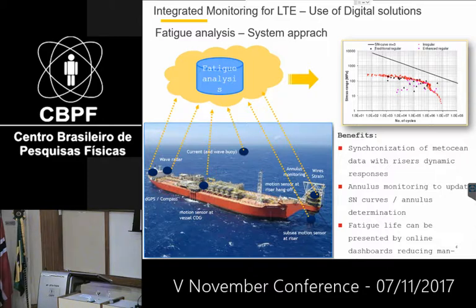We also are checking online Annulus gases that we use to update the SN curves, or also to understand the corrosion in the Annulus, the determination of the Annulus conditions. So we can put these in the intelligence here. And I would say that if you do this approach, we can follow the fatigue life in dashboards, and we really can reduce man hours with the team that will work to collect all data and do the assessments occasionally. So I believe you can use the digital solutions, we would say, to reduce costs for a lifetime extension.